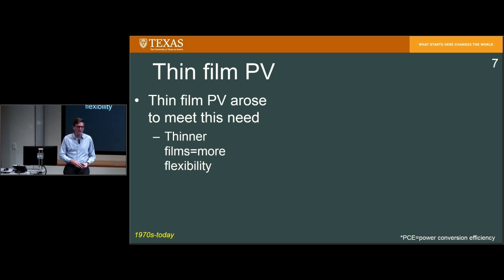So thin film PV, the general idea is, well, why are we using a poor absorber to make an absorbing photovoltaic device? We should use a very strong absorber. That way we can reduce the thickness of our films from the 100 microns to 1 millimeter I was talking about earlier, and thin your active layer down to about 1 micron in thickness. This allows for more flexibility, not because the materials themselves are any more or less flexible, but just as you get thinner and thinner, down to a micron or less than a micron, any material, everything being equal, will always have more flexibility to it. If you don't believe me, start chopping down a slice of wood and see how a thin slice of wood is more flexible than something that's fairly thick, like a board.